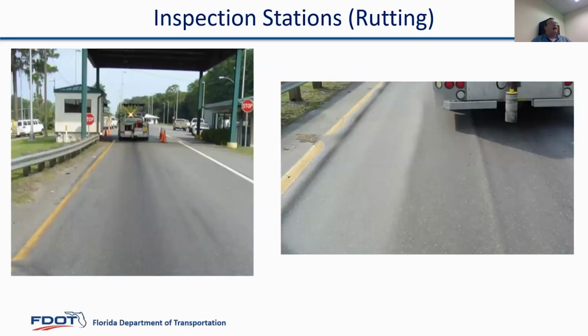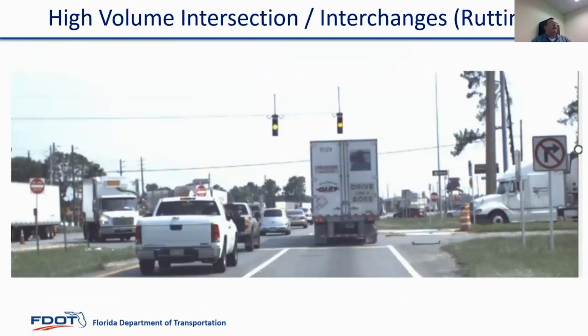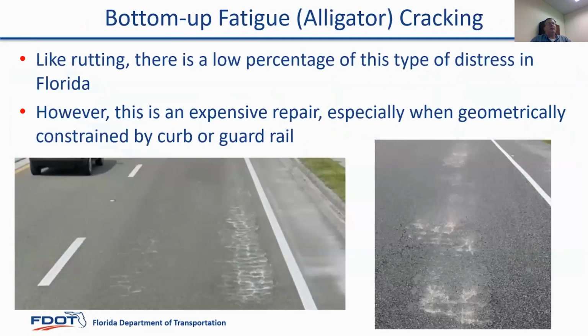Places where we've got really heavy and slow loads, like inspection stations. You can see that's an old 76-22 mix there. We got a lot of rutting at that inspection station. Also, high volume intersections or interchanges. This is the intersection at US 301 and I-10 near Jacksonville. You can see there's multiple truck stops there, a lot of trucks. That's a perfect place where we look to use the high polymer binders, an intersection like that where we want the best possible performance.